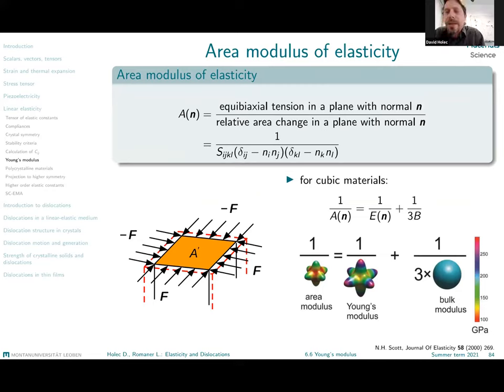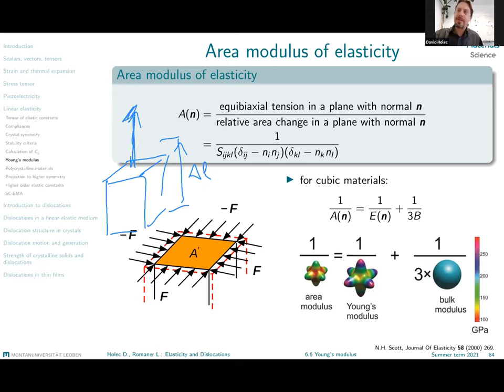As a counterpart to Young's modulus, which represents a uniaxial stress and uniaxial loading, I present here a slightly exotic mechanical property, a mechanical modulus called the area modulus of elasticity. For Young's modulus, we applied a force in a certain direction and we measured the elongation in this direction. Now we take the same sample and instead of this uniaxial force, uniaxial stress, we apply a biaxial stress. So we apply a stress which is perpendicular to the given direction and is the same stress in all directions. So the resulting stress is everywhere the same.